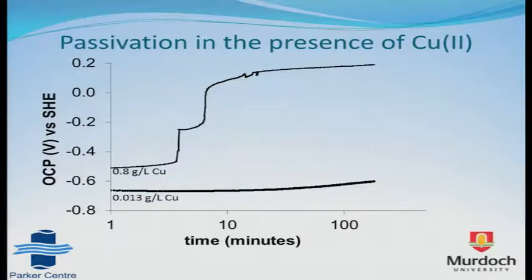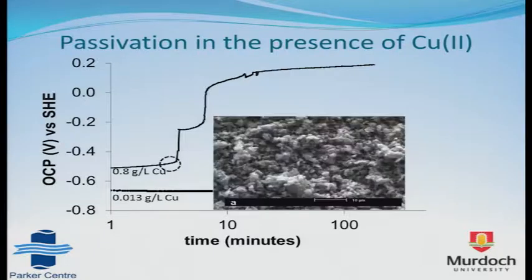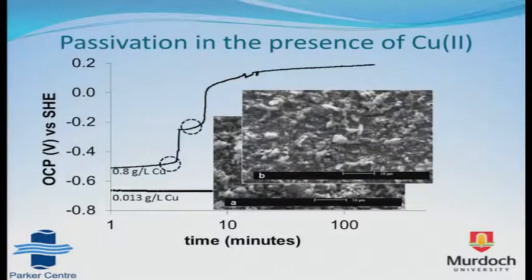In the case of a higher copper concentration, you see there's a change in the open circuit potential. So initially, again, there is a potential which remains in the active region, and there's a deposition of copper on the iron surface. But then there's a steep transition in the open circuit potential to an intermediate potential. And observation of the surface shows that there's still some copper on there, but it appears to be thinning. And this potential at which the electrode pauses for a moment is actually the potential of copper dissolution. So the iron dissolution has ceased, and now the copper starts redissolving. So it's no longer acting as a cathode, it's anodically dissolving.